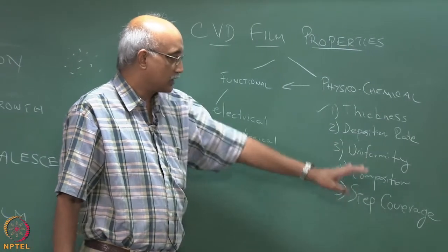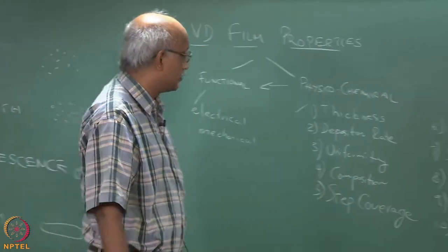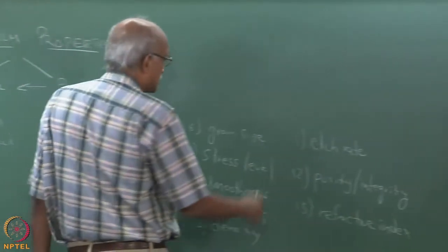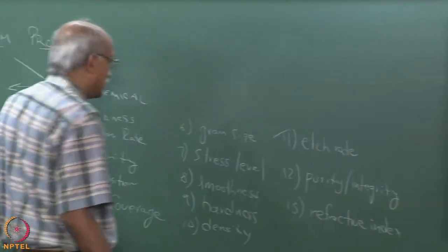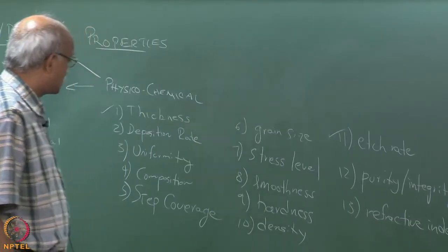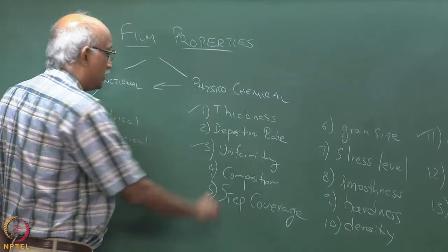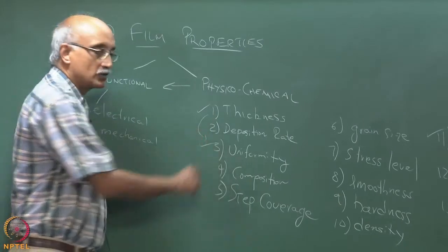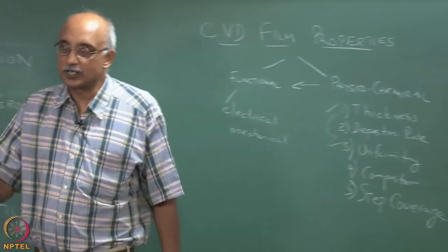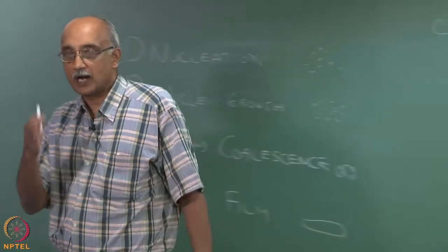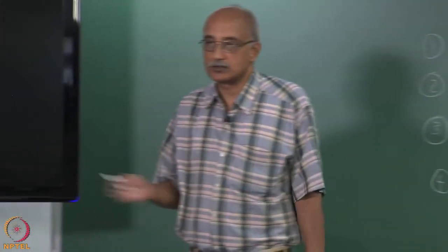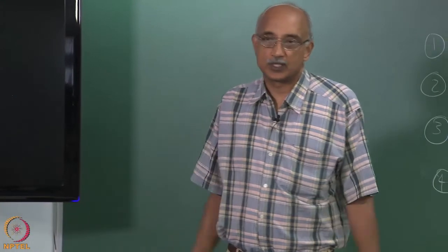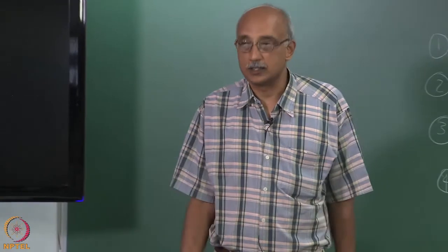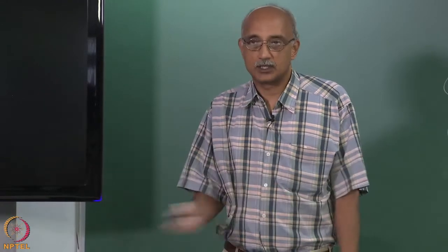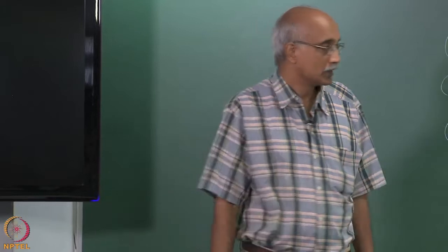So for all these tests, the one that would be done most frequently would be the thickness and the etch rate test, and uniformity, of course, will be looked at as part of the thickness measurement. Essentially, when you do the thickness measurement, you don't do it at just one place. You randomly select several locations on your substrate and measure the film thickness, and that gives you an idea about how uniform the film is. Okay.